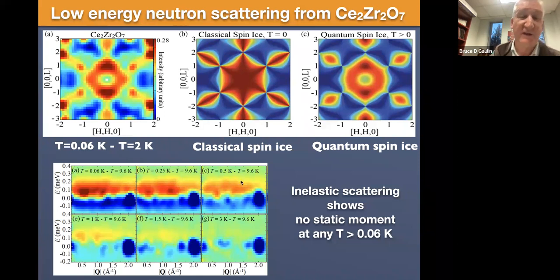There's kind of two things that I'd like you to notice here. One is that if you look around zero energy transfer, there's essentially no change or no growth in the elastic scattering in the zero energy channel that you can see here. And so this is telling us that there's no elastic component to the scattering, and essentially there's no static moment for any of the temperatures that we're studying, which are temperatures above about 60 millikelvin.